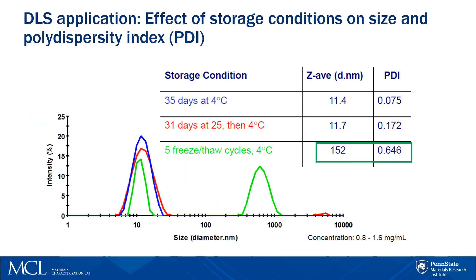This slide shows one of the DLS applications. The study was focused on how storage conditions affect particle size. Samples were stored at three different temperature regimes and then measured by DLS, which provided size distribution — percent intensity on the y-axis and particle diameter in nm on the x-axis.